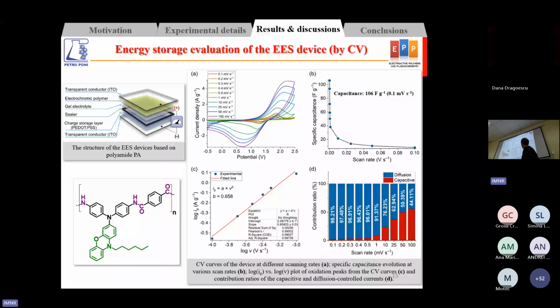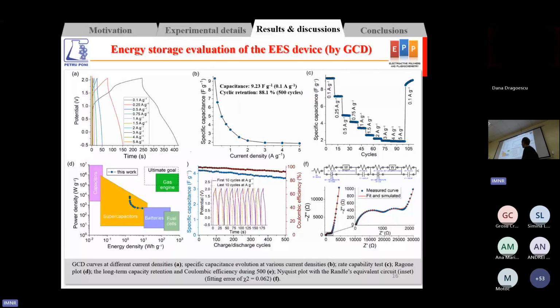batteries. Also, the energy storage was evaluated by galvanostatic charge-discharge by applying different current densities. From the curves, we extracted the capacitance and obtained around 9 farads per gram. Also, we tested the stability of the charge-discharge process up to 500 cycles. According to the results, the device based on this polymer showed parameters around the boundary between batteries and supercapacitors.